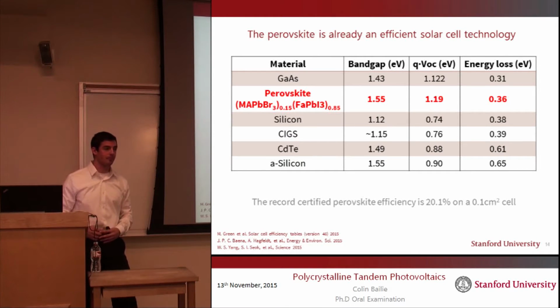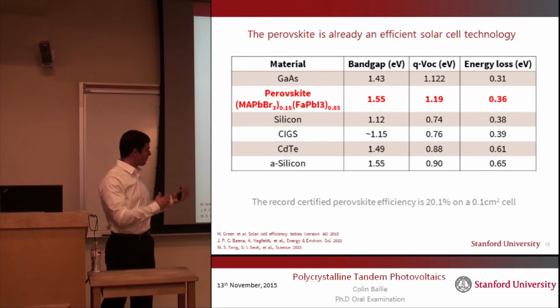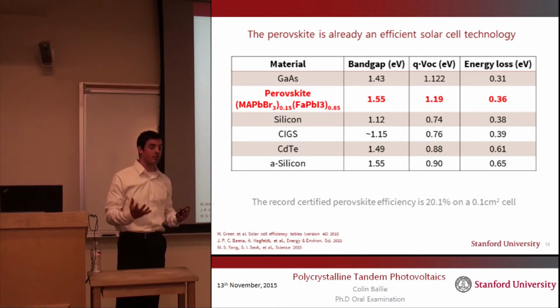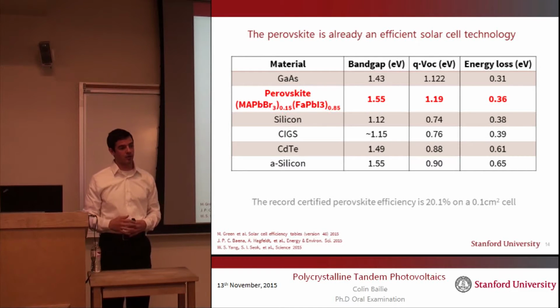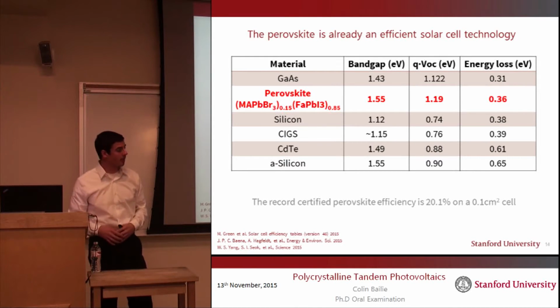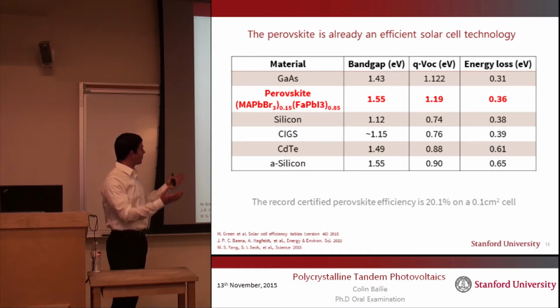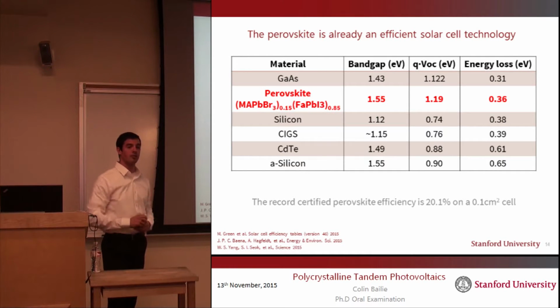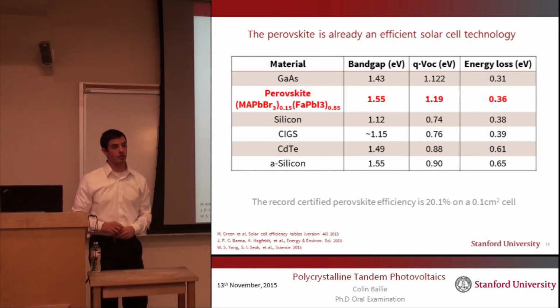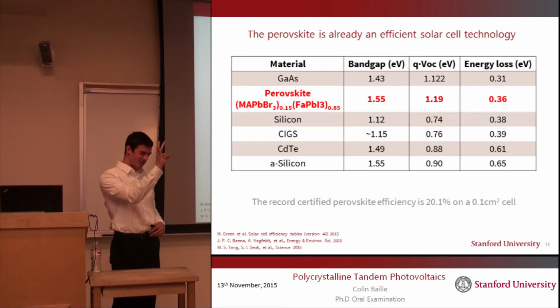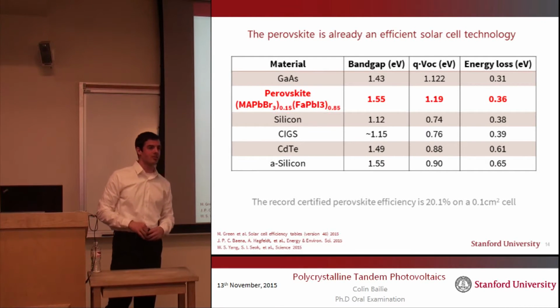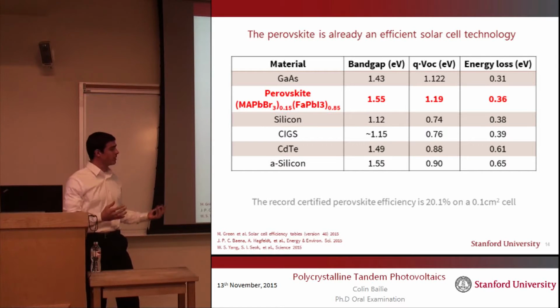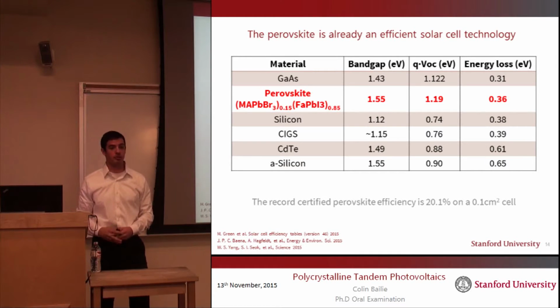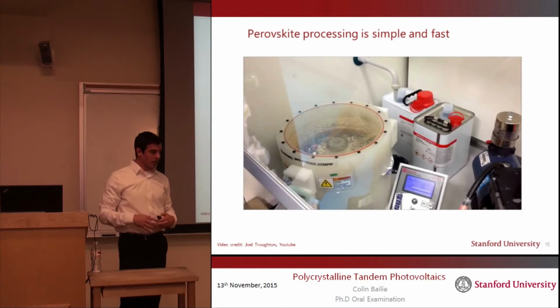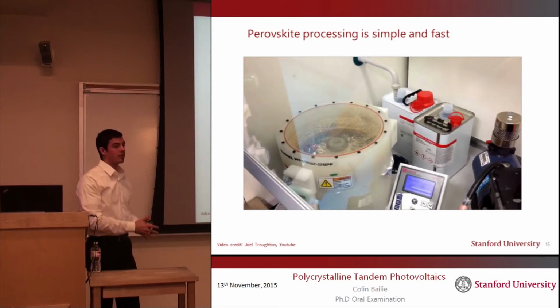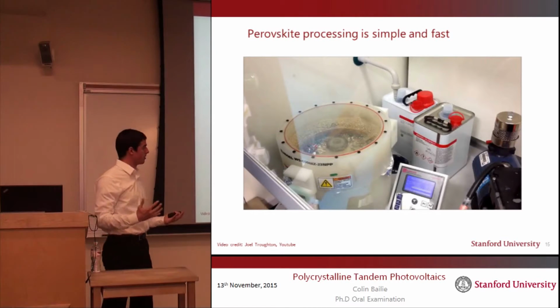cadmium telluride. And moreover, the perovskite makes an extremely efficient solar cell with the certified record efficiency above 20%, which puts it on par with both CIGS and cadmium telluride, which have record efficiencies of 21%. Now, this was only on a 0.1 centimeter squared device that you can barely see with the naked eye, but nevertheless, it provides a proof of principle. And it's also compatible with this low-cost processing that I was mentioning before.